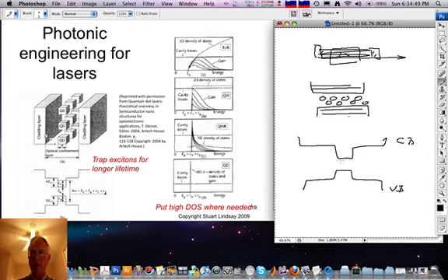In the region with the quantum dots in it, the energy states for holes are made lower. Remember, going upwards in energy for a hole means lower in energy, and the energy states for electrons are made lower, so that electrons from the conduction band tend to fall into this region of lower energy, and holes from the valence band tend to fall into this region of lower energy, so that excitons then can stimulate optical emission from these quantum dots, which themselves have energy focused in the region of resonance of the surrounding cavity.